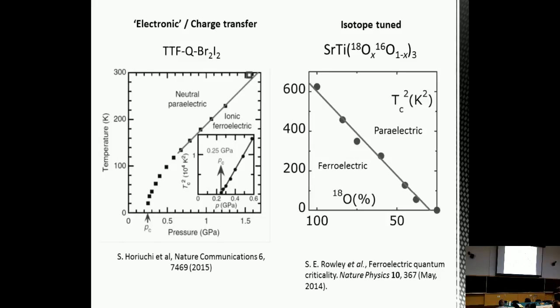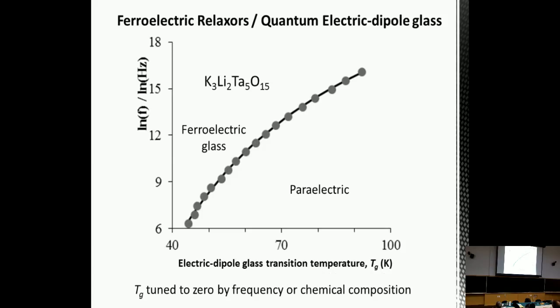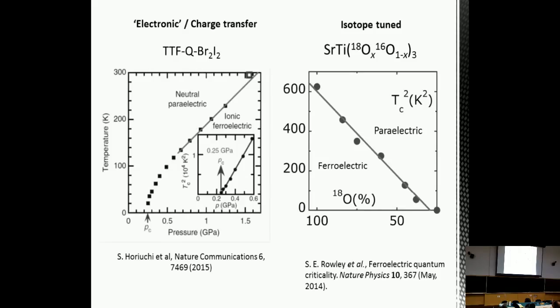We also have the electronic or charge transfer type of ferroelectric, where in this case, in the paraelectric phase, there are no charged ions in the lattice, but at the transition, electrons move from one atom to another, thus creating ions and a ferroelectric state. So here, this is due to the motion of electrons rather than the motion of ions. And again, in this case, this work from Japan, you can tune with pressure to a quantum critical point down here.